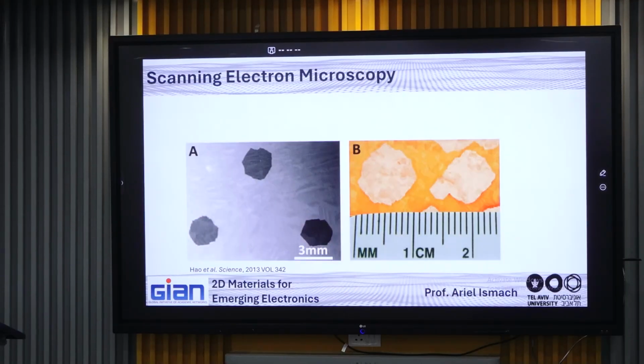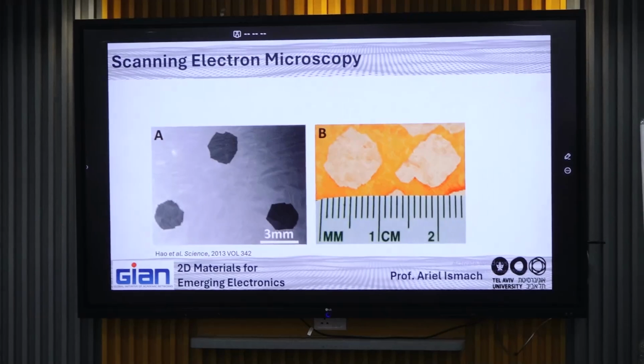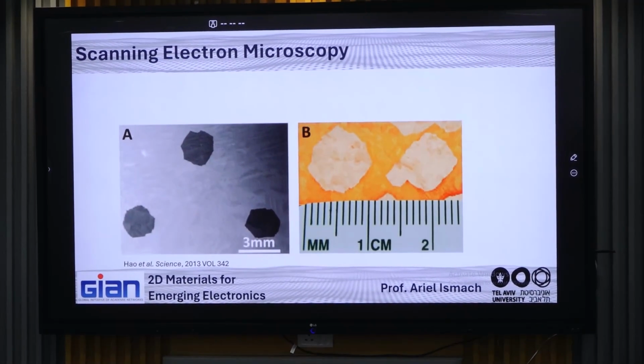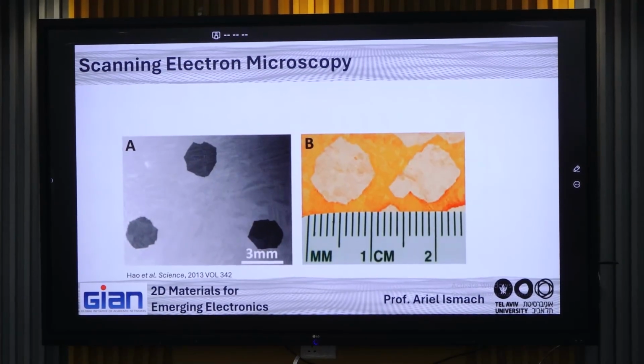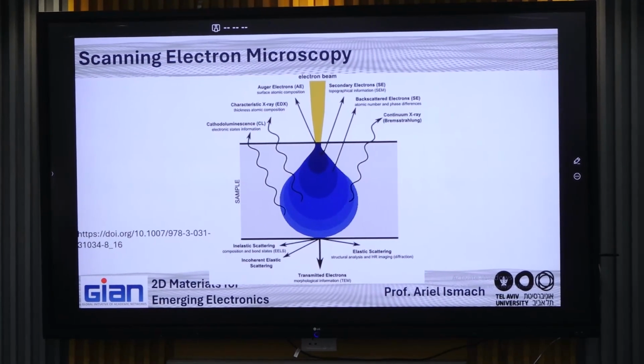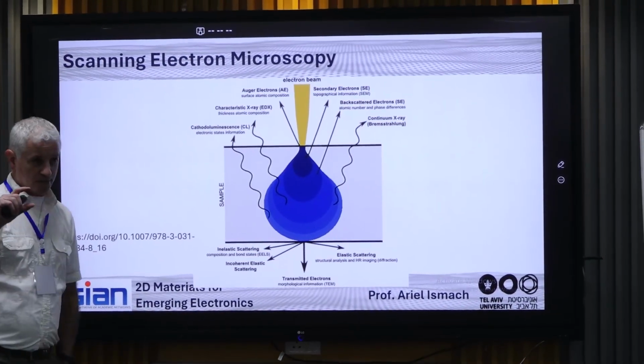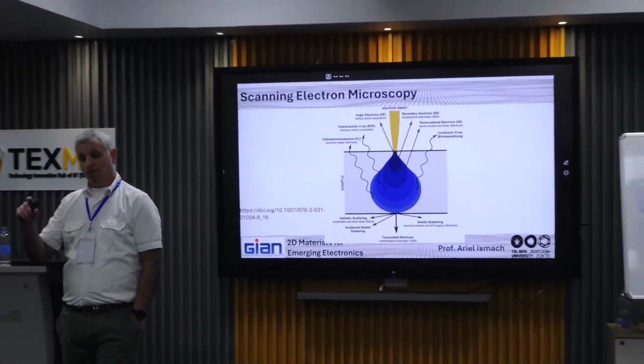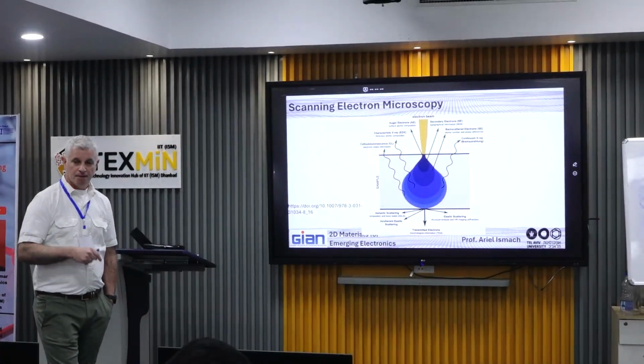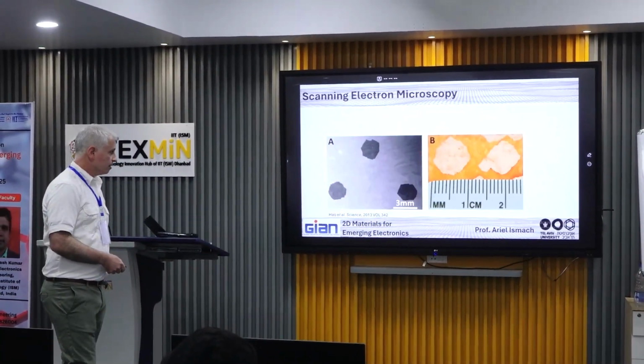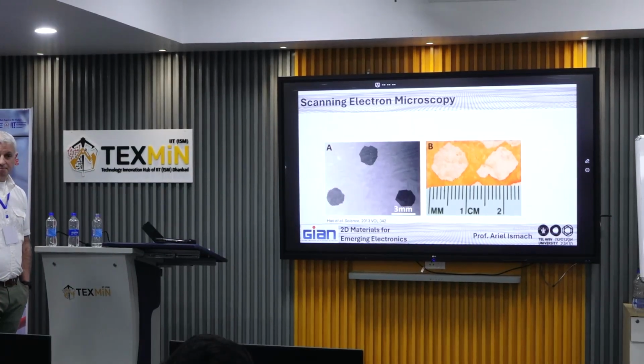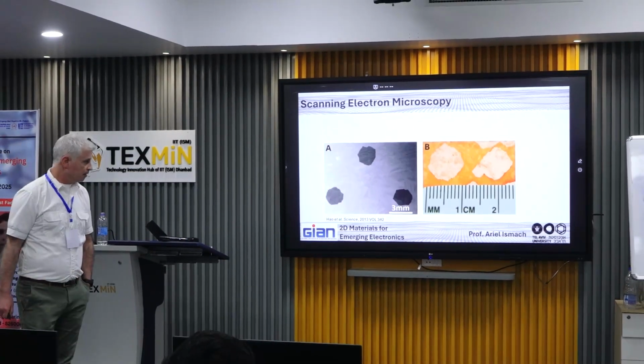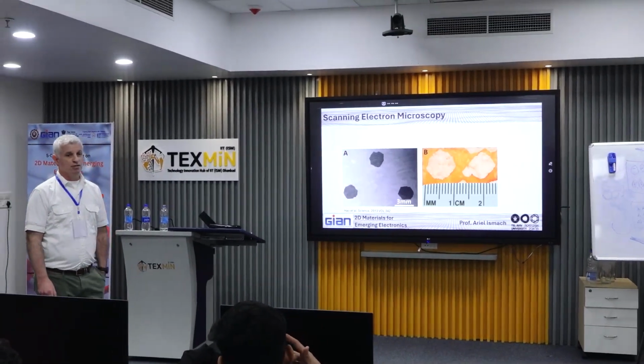So again, here you can see the comparison of the backscatter electron detector SEM on the left, and the optical microscope that you already saw. And you see again that we have a very strong contrast. And again, the question is, how do we explain that? Charging effects. The secondary electrons, despite the fact that they are sensitive to the surface, and surface means a few nanometers deep, not the atomic layers. So how does it come that we have such a good contrast between the graphene domains and the substrate? Charging effects, yeah.